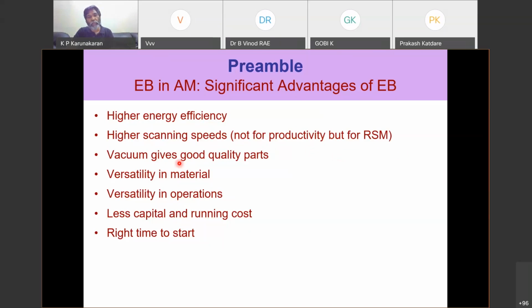Now, the second important advantage of additive manufacturing is the vacuum environment. When you build the part under vacuum, the component is completely free from any kind of inclusions. Okay, even if you build it under argon, the porosities will be filled with argon. Whereas when you build under vacuum, even if you have porosity, the pores are void. So the integrity of the part you produce is extremely high when you build it in vacuum. Initially, people were reluctant because vacuum costed money, but today vacuum pumps have become affordable. And people said, once you start the machine, you have to wait till vacuum builds up, and then when you stop the machine, you have to wait till the vacuum is released.